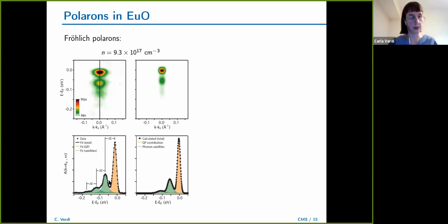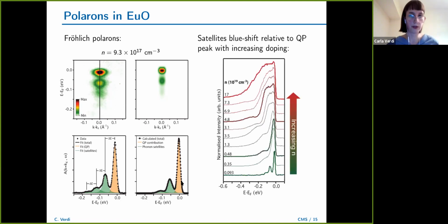You see that actually the intensities that we get for our spectral function profile are not exactly matching the experiment. This could be due to various effects, but of course, we didn't actually look further into this. What we looked more into is this. So in the experiment, you could actually see that when you increased the doping level, the satellite would blue shift relative to the quasi-particle peak. So you see this is low doping, and then you increase the doping and the satellite moves further and further, and then at some point you don't even resolve it anymore.